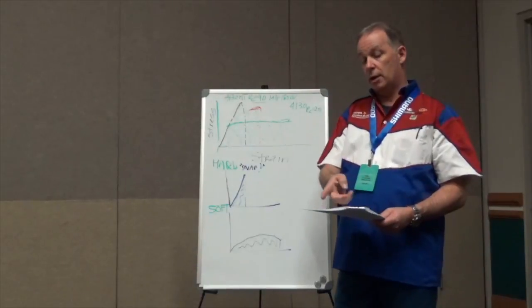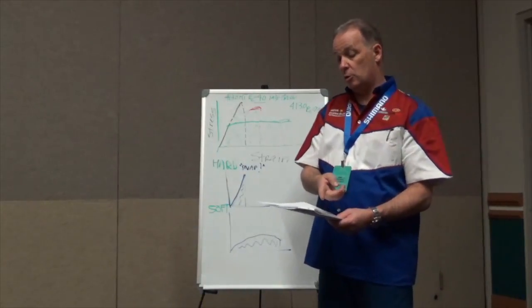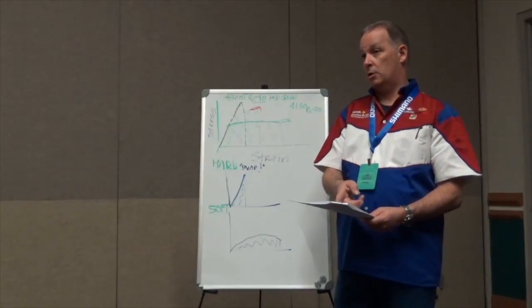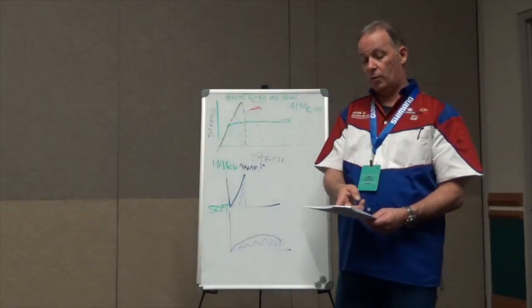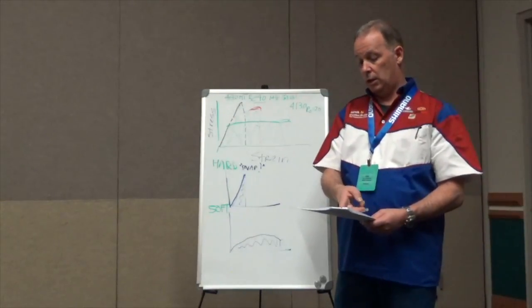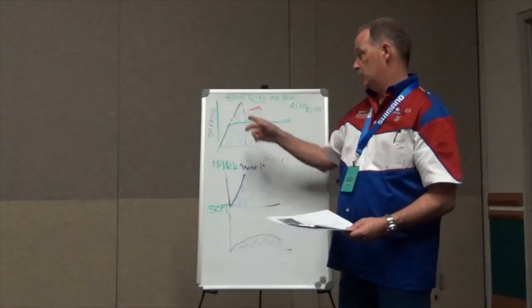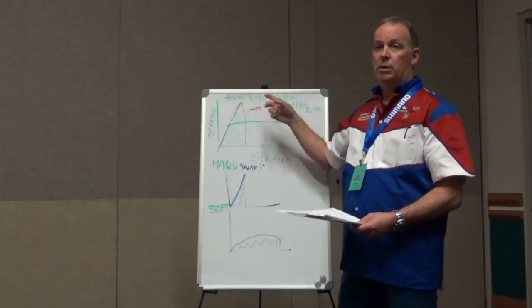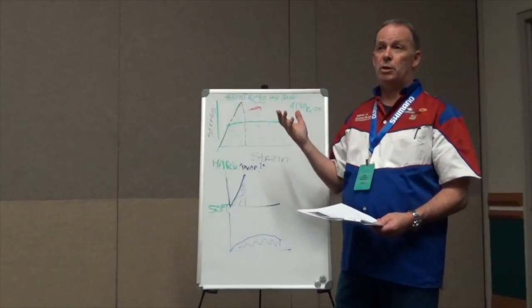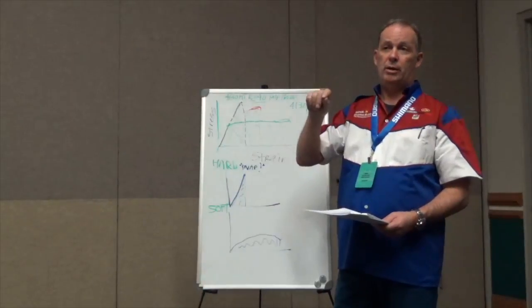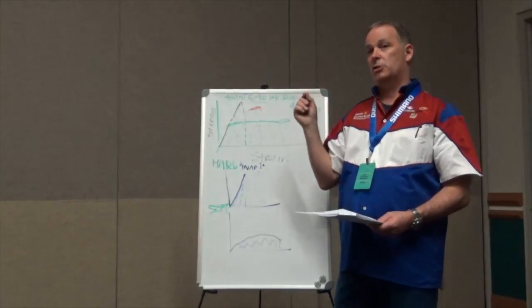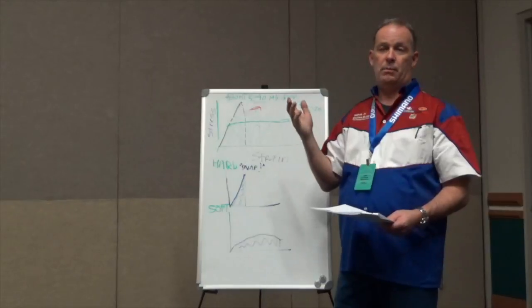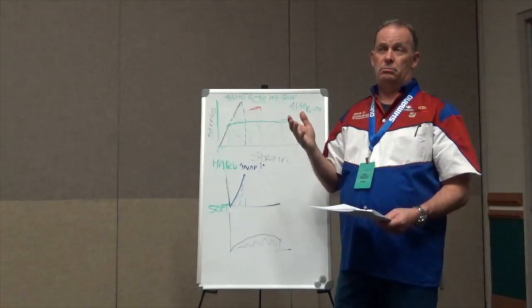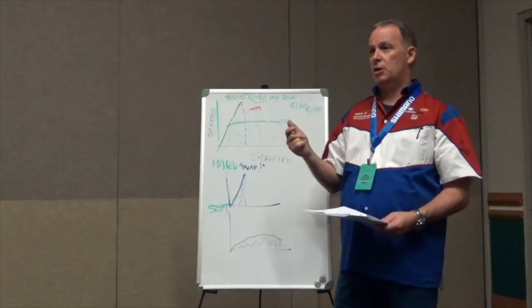You see these rings. These are cutoffs of tubes where we cut them wet so that there's no thermal thing going on with them. We deburr them, and then we use a lab-grade hardness tester to get a Rockwell measurement. You can go to almost any engineering handbook. You can correlate a Rockwell hardness to a tensile number. Machinery's Handbook has a little bit of that stuff.